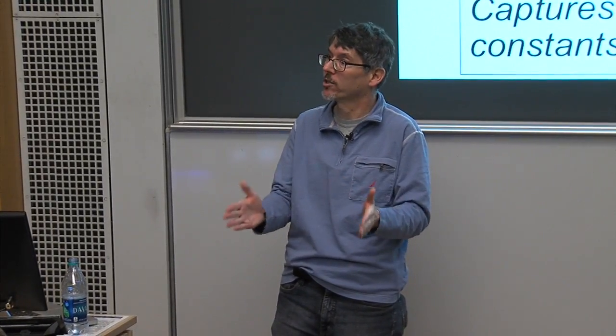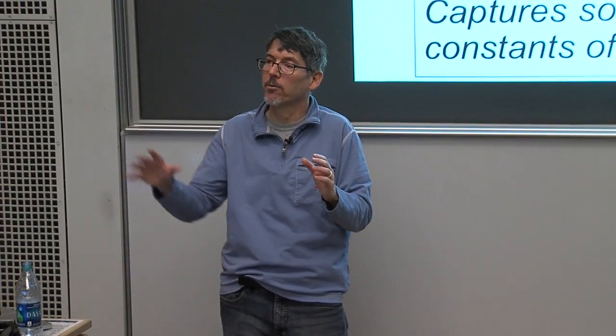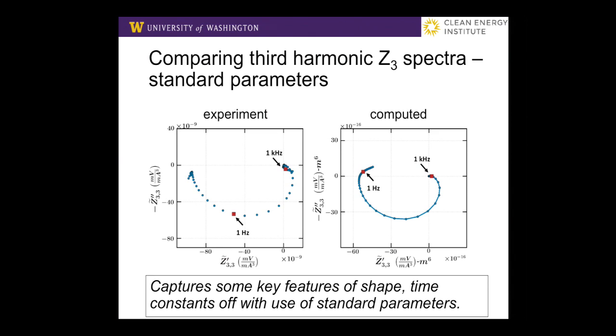We've got data, we have models, and we have now extra information about what's going on by looking at the linear and the nonlinear harmonics. The low frequency stuff has thermodynamics and transport in it. The middle to high frequencies have information about the charge transfer in it. The highest frequency in the linear tells us about the electrolyte resistance. All of that is tied into those 20 parameters in complicated ways. And now we're sorting through how we find our parameter sensitivity so that we can really begin to understand what's going on there.